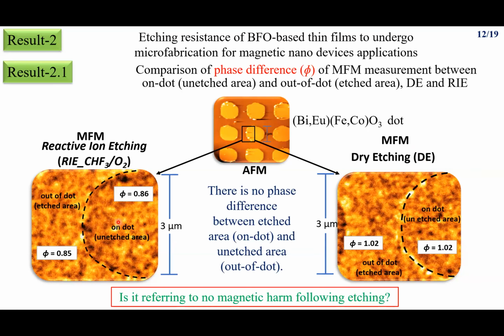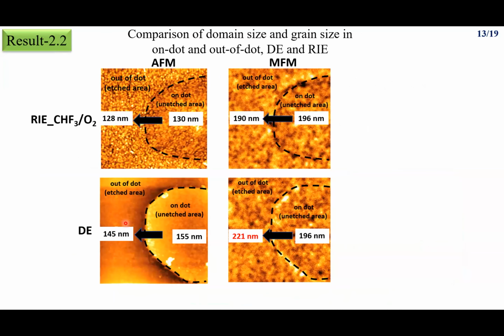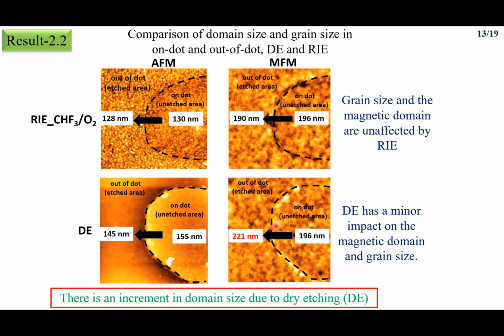But when I checked their phase difference, there is no change, but only from the phase difference, I cannot say that there is no magnetic damage. To confirm it again, I considered the change in domain size and grain size. In the case of reactive ion etching, I could find there is no change in the domain size and grain size, but in the case of dry etching, there is an increase in domain size, that is leading to the magnetic damage.